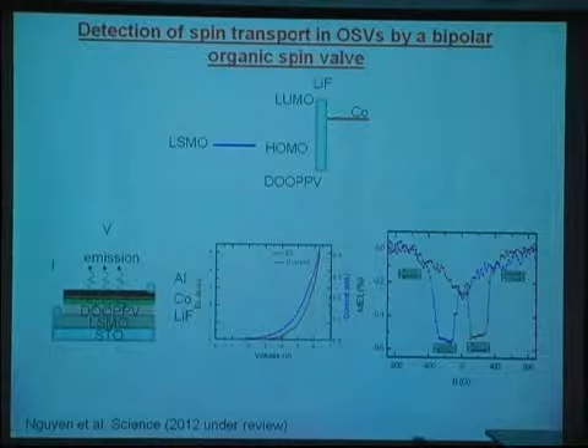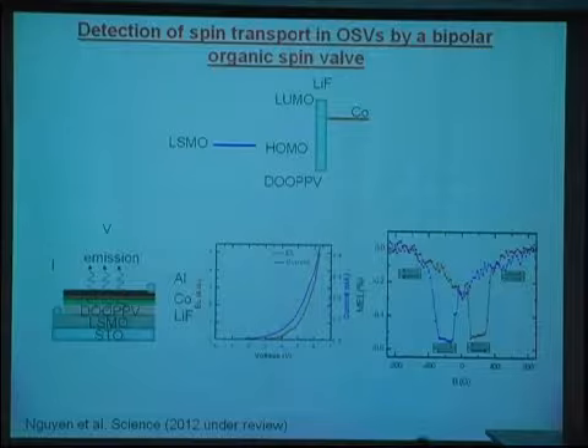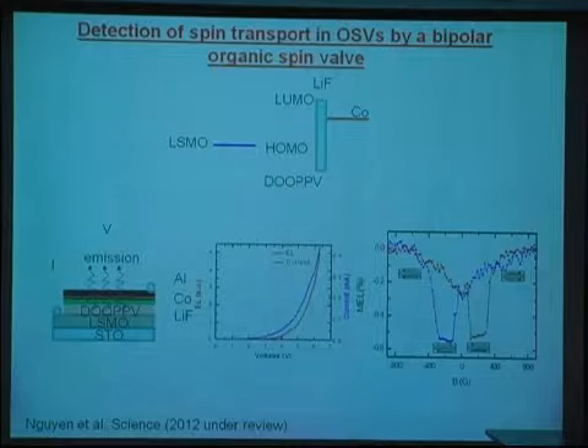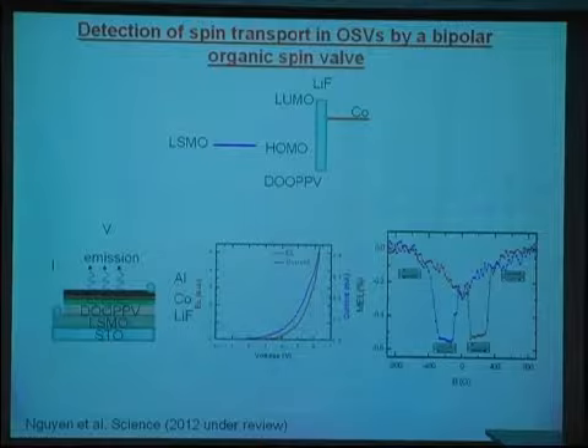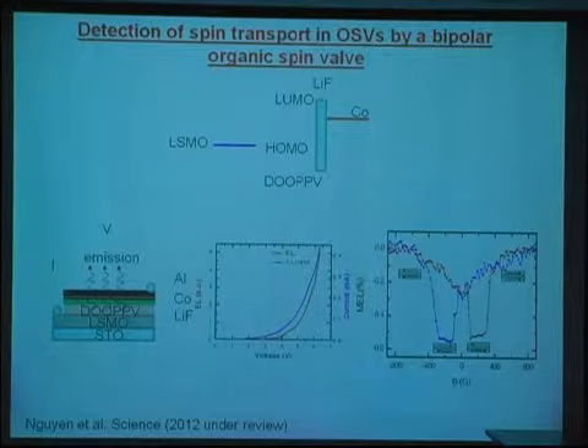Lithium fluoride is the insulator, a polar insulator. Yeah, this is LSMO, DOOPPV, and we have the lithium fluoride and cobalt, and we have to protect the cobalt with aluminum. And the thickness of the aluminum and cobalt layers needs to be less than 10 nanometers in order to allow the light to escape from the device.